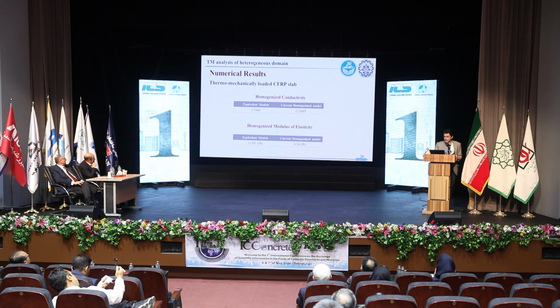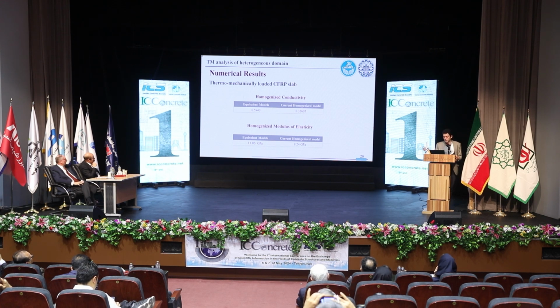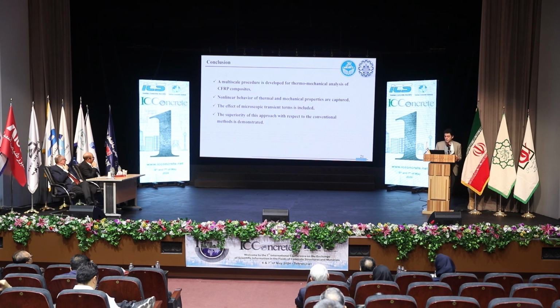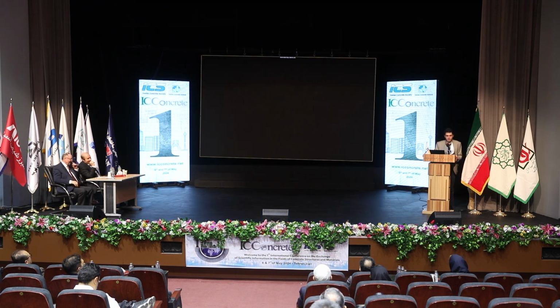And you can see the equivalent values in the conventional equivalent models in comparison to our calculated homogenized models, and there is a significant difference between these values. As a closure, we proposed a multi-scale procedure for thermo-mechanical analysis of CFRP composites. Nonlinear behavior of thermal and mechanical properties is captured. Also, the effect of microscopic transient terms can be included in this model, and the superiority of this approach with respect to the conventional equivalent models is demonstrated. Thank you for your consideration.